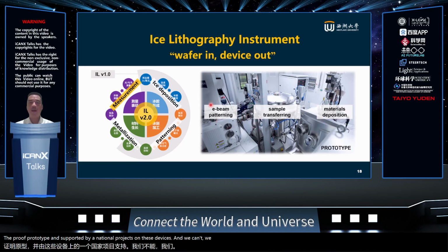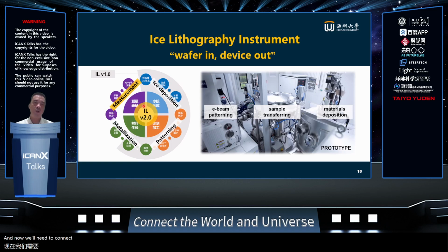And we can realize e-beam lithography, and we can do the sample transferring from the e-beam to material deposition in the same vacuum, easily. So we are trying our best to realize a wafer-in, device-out, all-in-one nanofabrication ice e-beam lithography instrument. I think we have already achieved roughly 60% of our goal, and we are still working on this. So this is what we have already realized, part of them. And now we need to connect all these parts together and make an even more complete device. We still have a few years of work to do.